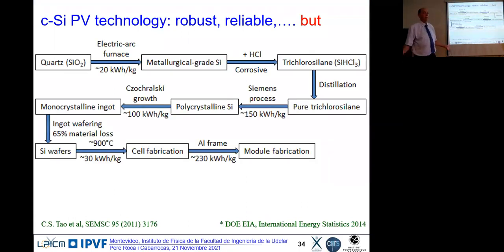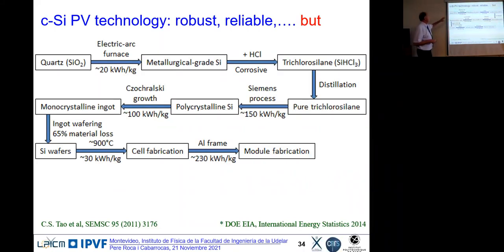So it's crystalline silicon. C'est fini. It's done, right? I mean, once I have said this, gigafactories, crystalline silicon, it is forever. Well, I am coming from thin films, so I have been spending time on thin films. When you look at the full value chain of crystalline silicon, you start with quartz, which has to be pure. You want to purify this silicon to make metallurgical grade silicon. Then you distill using HCl to make trichlorosilane. If this trichlorosilane is distilled, you use the Siemens process to make polycrystalline. Then you make the ingot from the polycrystalline, and from the ingot the wafers, and the wafers make the cells.